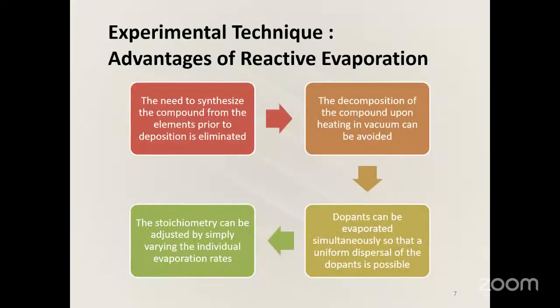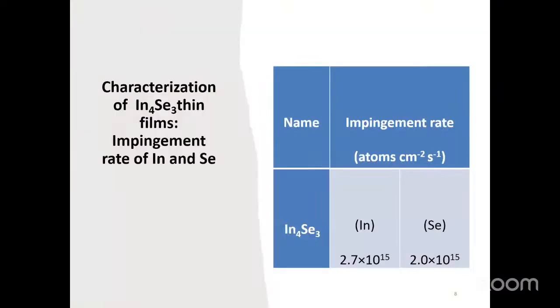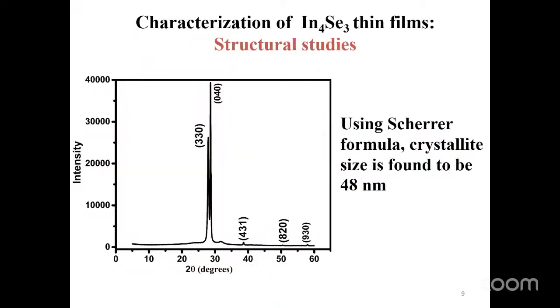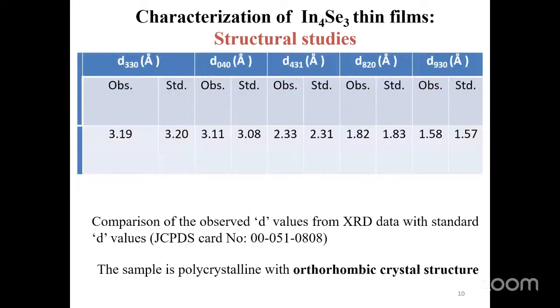Now, in the present study, the impingement rates of indium and selenium are 2.7 into 10 raised to 15 and 2 into 10 raised to 15 respectively. Now, this is the X-ray diffraction pattern of In4Se3 thin films, and using the Scherrer formula, the crystallite size is found to be 48 nanometer.